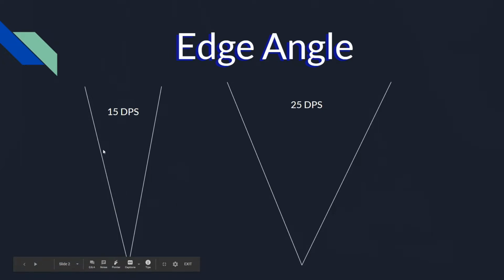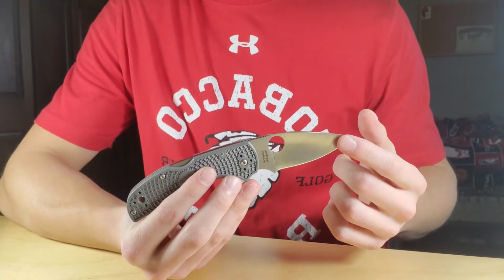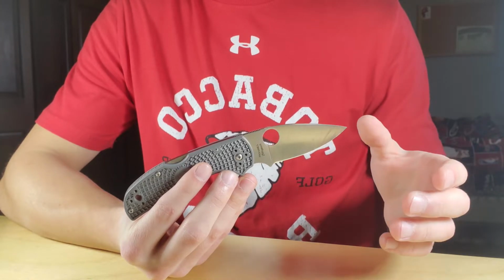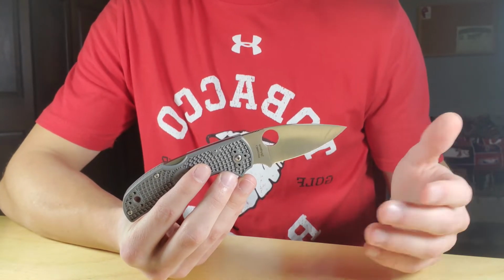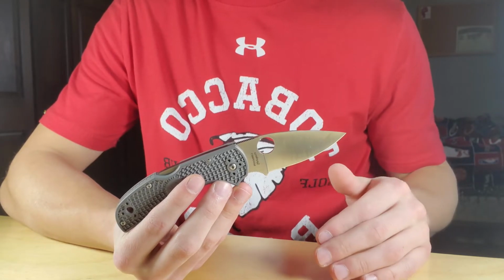Now, if you look over here at the 15 degree per side one, and my slide thing keeps popping up here, so it's kind of hard to see, but it stays thinner for way further up here. So let's say this point right here is the point that it becomes dull. To get to that width over here on the 25 degrees per side, you probably have to go half that distance. So being at a lower edge angle like that increases your edge retention just because the actual apex stays smaller for a longer period of time. The amount of wear for a 15 degree per side edge to get dull is significantly more than a 25 degree per side edge to get to that same point, just because like we looked at on that PowerPoint slide.